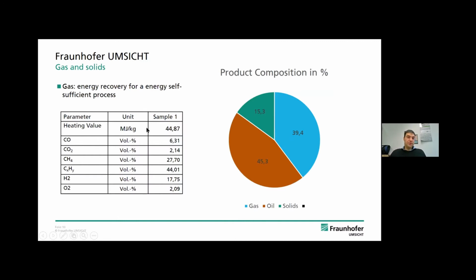And next, I want to have a deeper look into the composition of our products, for example, the pyrolysis gas itself. So we have a very high heating value of around 45 megajoule per kilogram. And the composition is mostly CxHy, so alkanes, with around 44%, but also quite a lot of methane. So in total, these are around 70%. Then we have around 18% hydrogen, which makes it a very interesting gas, also if you are thinking about substituting natural gas.